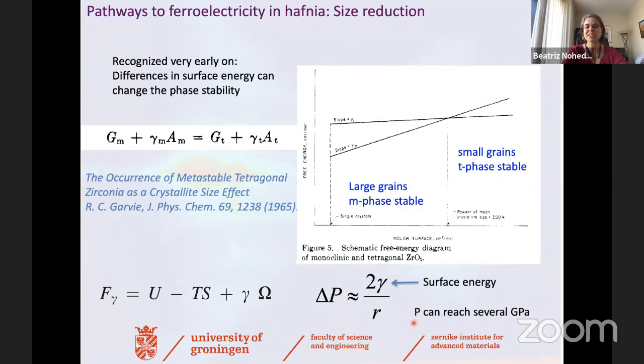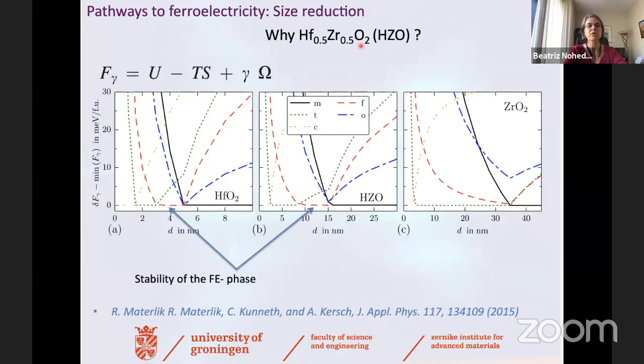And these internal pressures can reach the order of several gigapascals. So they can really change the stability of phases in this material. So indeed, it seems like one can go to this high temperature tetragonal phase by reducing the size. And that's why the polar phase of hafnia was only found at a really low thickness or low sizes.